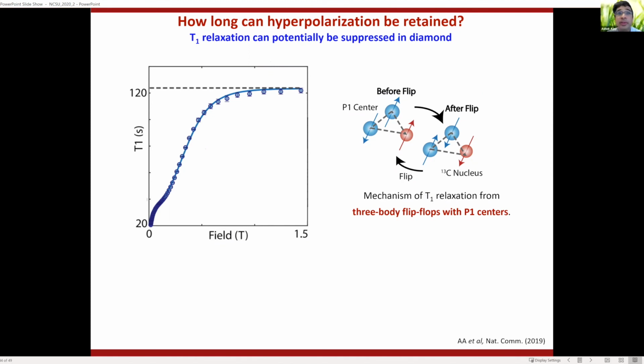It's an excellent question. So, this nitrogen can be N14 or N15, and usually it's N14, which is a spin 1. It has three transitions basically, and we see this all the time. People doing NV detection see these N14s a lot. The problem with them is, they're not too useful. They're useful in the sense that you can make a very good memory with them. So people have used them in the past when you have information that's stored from the NV center. You can store them in the N14 because they'll live longer and whatnot.